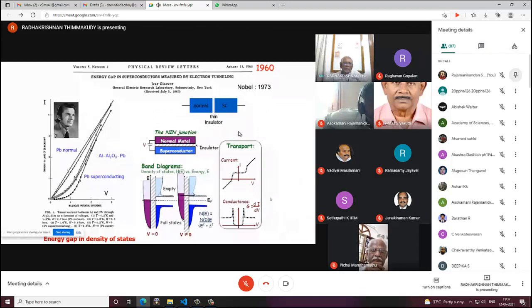So he started tunneling. He measured current voltage characteristics in this kind of sandwiches. For example, normal superconducting sandwiches with a thin insulator. And then he got current versus voltage. When the temperature is high or even when voltage is low, he got normal tunneling, essentially a straight line relation between the current and the voltage. But then as you make lead one of the components, aluminum oxide, lead superconducting at low temperature, 4.2 or 1.6, etc., then the energy gap appeared in a superconductor, and then you cannot, of course,